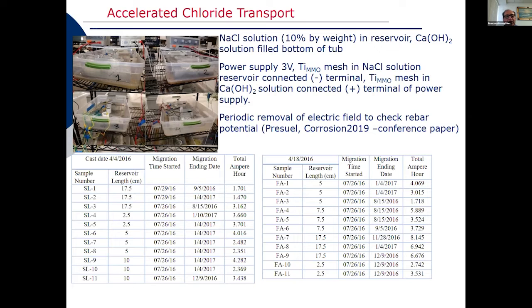The potential difference initially was up to 3 volts. This was reduced if too much polarization of the rebar was taking place, and this was conducted for a period of time. The reservoir was placed about 2 months after the sample was prepared, and the number of days that you will see later start from when the solution was placed in the reservoir. The table that you see there shows the total ampere hours that were applied to each one of the single rebar specimens for a couple of the compositions that we're using here.